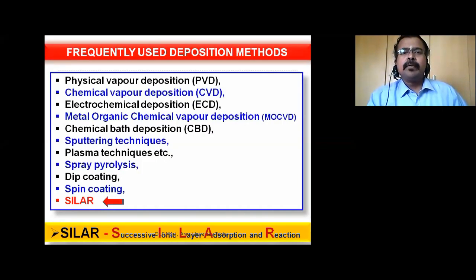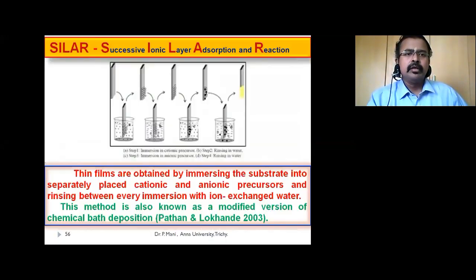Then frequently used deposition methods: PVD, CVD, ECD, MOCVD, sputtering techniques, plasma techniques, and spray pyrolysis, dip coating, spin coating, and finally SILAR, which we are using in our lab. SILAR is successive ionic layer adsorption and reaction. Thin films are obtained by immersing the substrate into separately placed cationic and anionic precursors and rinsing between every immersion with ion exchanged water. This method is also known as a modified version of chemical bath deposition.